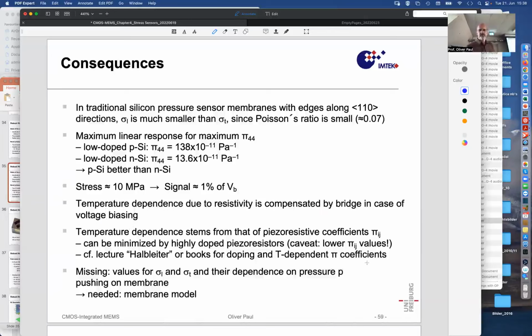And while that due to the pi coefficients remains, that could be minimized by having highly doped piezoresistors. Highly doped piezoresistors are less sensitive to temperature, but then you lose piezoresistance because they are also less sensitive. So it's a matter of, again, trade-off. Do you want a cheap part, but not such a high performance sensor, or do you want to have a high performance sensor? And then you need to invest something for compensating the temperature.